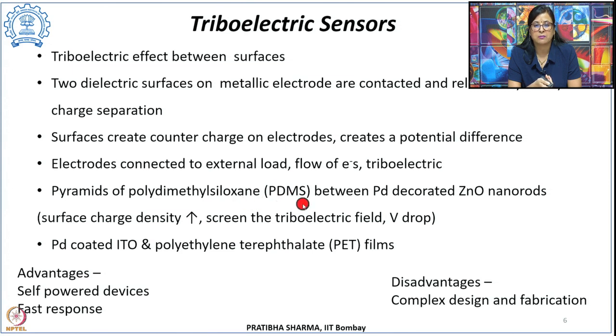So, PDMS has been used, and that is between the palladium decorated zinc oxide nanorods. Now, the palladium has a higher work function. So, there is a surface charge transfer from zinc oxide to palladium that will take place, and what will happen is the adsorbed oxygen, in the absence of hydrogen, takes up the electrons, and as such there is a smaller number of electrons. However, when there is hydrogen also present, if the environment has